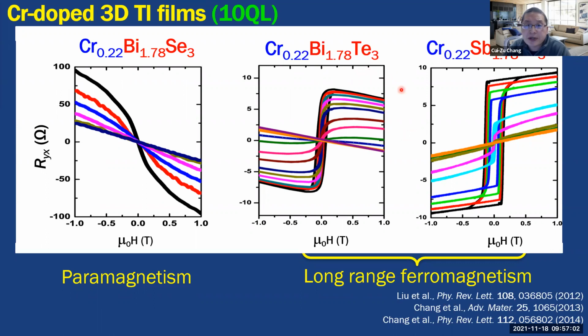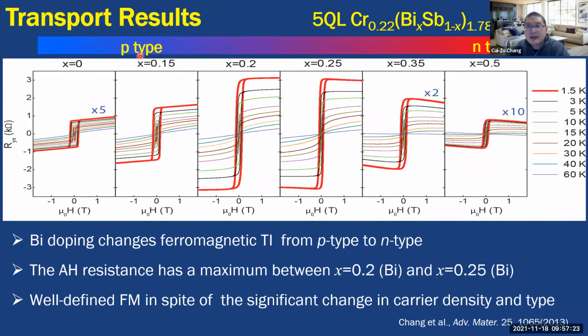And the very straightforward direction is we combine them together, we mix them together to grow the chromium-doped bismuth antimony tellurium film. This is the reason why we choose the 4-element topological insulators for the realization of the quantum anomalous Hall effect. So here, let's see the transport results. We need to tune the bismuth antimony ratio to make it become an insulator. If the sample is a good insulator, in principle, according to the theoretical prediction, we could realize the quantum anomalous Hall effect.